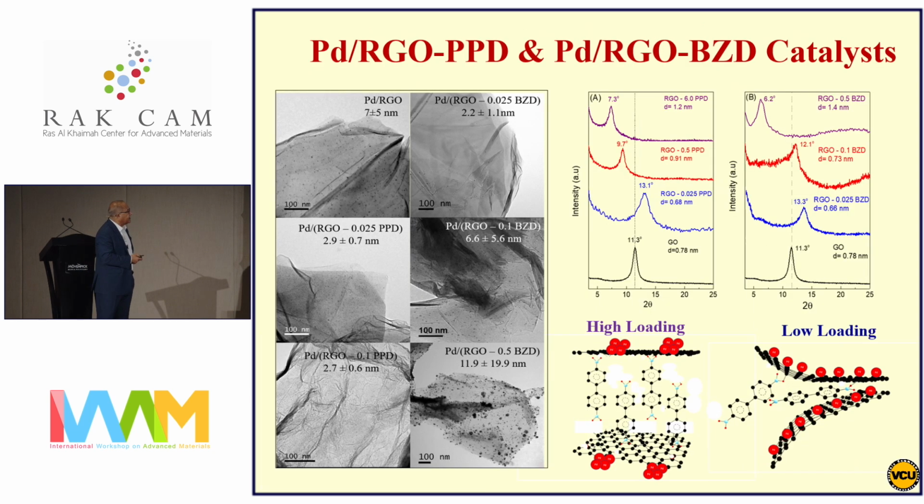And that's what we will see next. So you can, of course, get an idea about the spacing between the layers with the chemically modified graphene oxide here, looking at the XRD peaks and how they shift as a function of loading of the electron donor materials. As I mentioned, with a small loading, we see that the separation is less.